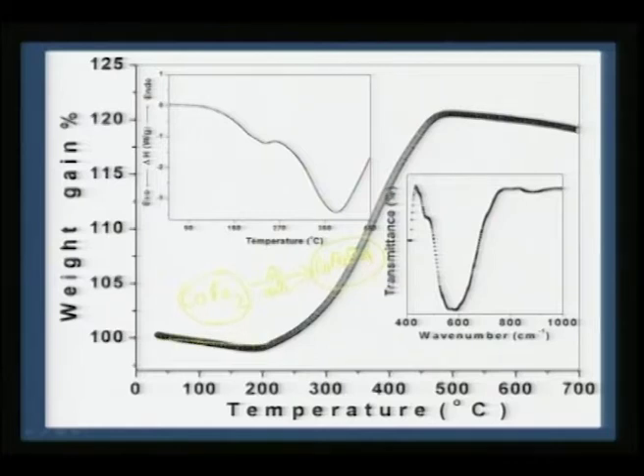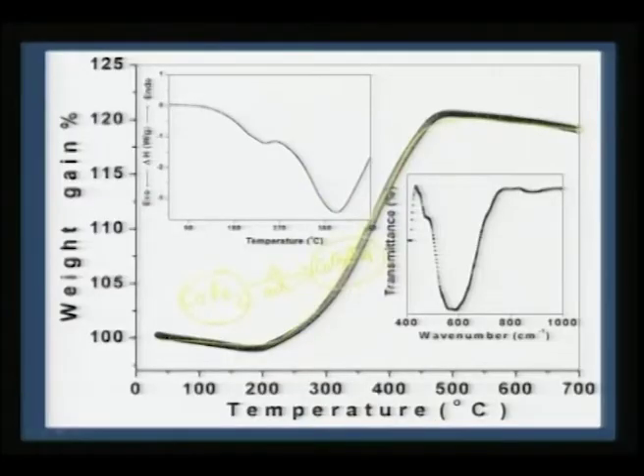Therefore it has to be a weight gain, and as you can see here, interestingly it shows a clear increase in weight, and this weight gain, say from 100 to 121, exactly corresponds to the weight gain that you would expect out of CoFe2O4. So just a simple TG technique can be used to ascertain what is exactly going on, and in this way we have made sure that you are exactly isolating an alloy powder of this form, and you can also see corresponding to that a typical endothermic conversion because there is a weight uptake due to conversion from alloy to oxide.